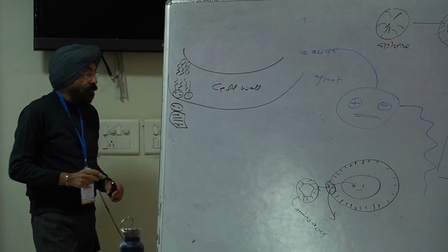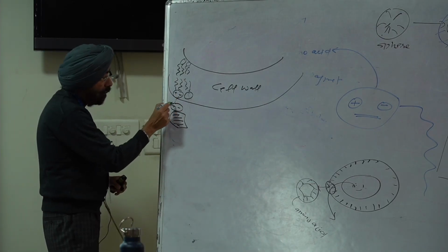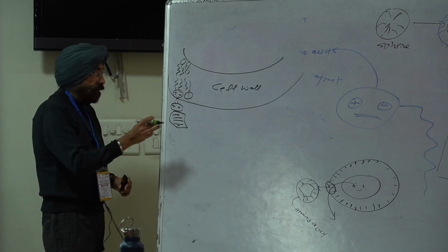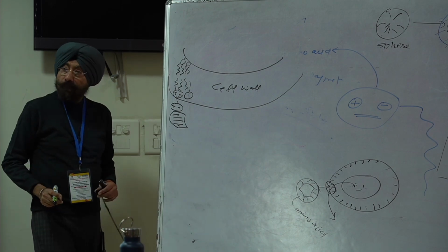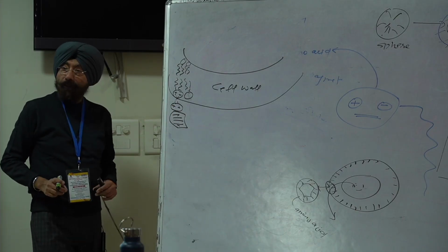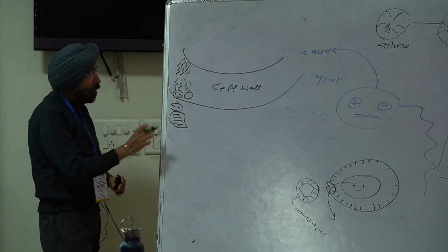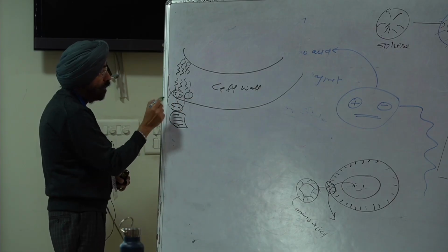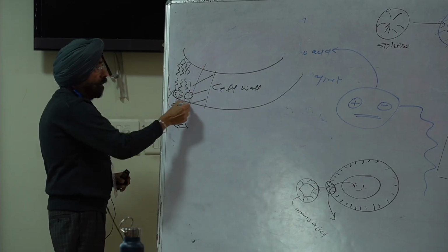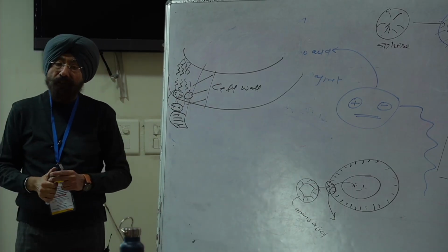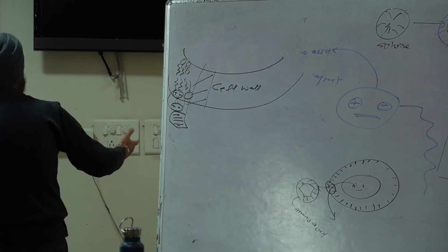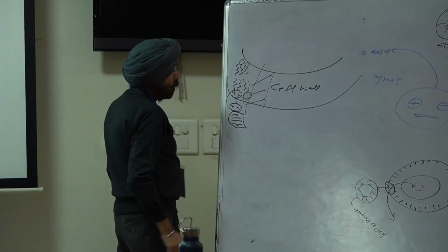It means that I am initiating the electrostatic interactions between the positive end of the head group with the acid group and the negative end of the head group with the amino group, ammonium group. Right? So in this way, the electrostatic interactions will disturb the cell membrane and hence it will break it, leading to the oozing out of the hemoglobin. So this is happening in the case of amino acids.